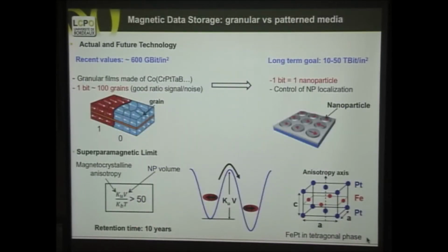Now, from the magnetic point of view, today we are at 600 gigabit per square inch, and you see a bit is many grains, many dipoles on the surface. Tomorrow, we would like to have 1 bit per nanoparticle, but in order for the magnetization of this nanoparticle to stay constant, we have to have a very big magnetocrystalline anisotropy, this parameter here, times the volume of the particle, against what I call the God-given noise, the kT. You have the temperature fluctuation, the Brownian fluctuation around, which depends on the temperature.